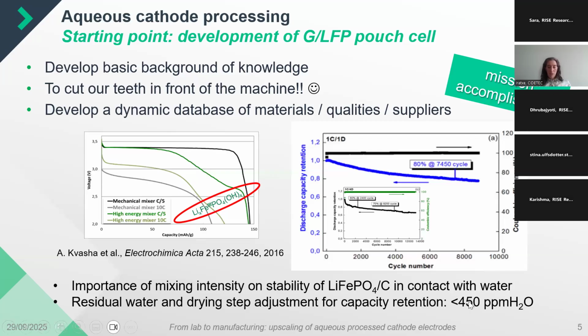But as I was mentioning, related to the drying step at the end, since there is a water-based slurry composition, some of these components will be more hydrophilic than the standard PVDF in NMP processing. We also have to be more conscious of the final drying step to be below a certain threshold in terms of residual water ppms remaining in the pores of the electrodes.